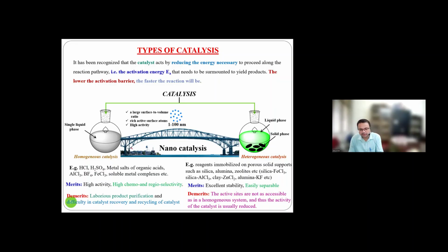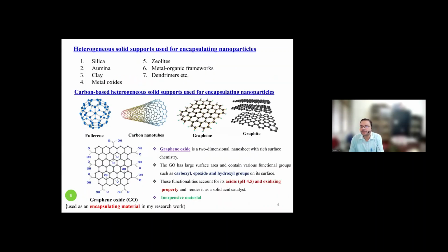But a disadvantage associated with nanocatalysts is their lifetime. The catalyst sometimes agglomerates in a very short time, so stabilization of the catalyst is one of the biggest challenges. People use stabilizing agents like silica, alumina, clay, zeolite, metal organic frameworks, and also some surfactants and polymers for stability. But among all the stabilizing agents, my interest goes to carbon materials because they are green, like graphite or graphene oxide.